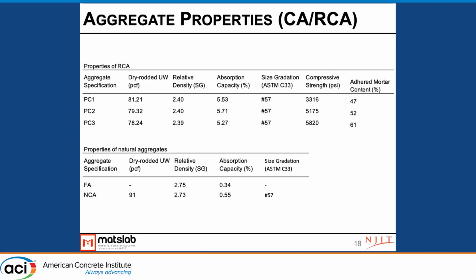So this is just showing the properties of RCA and the properties of the natural aggregates used in the study. What I really want to point out in this slide is the absorption capacity. The absorption capacity of a natural aggregate is going to be about 1/10 of what we would see in RCA. So when you're actually mixing RCA, it's very important to be careful about how you condition it, and definitely add enough water to that system, because if you don't, the old mortar phase is going to suck up a lot of the water that you're adding to the system, and you can end up with a really bad mixture. It's more important for RCA to get your aggregates to an SSD condition so that you can actually use it in mixing. And if you look at most studies involving RCA, this is definitely an important factor.